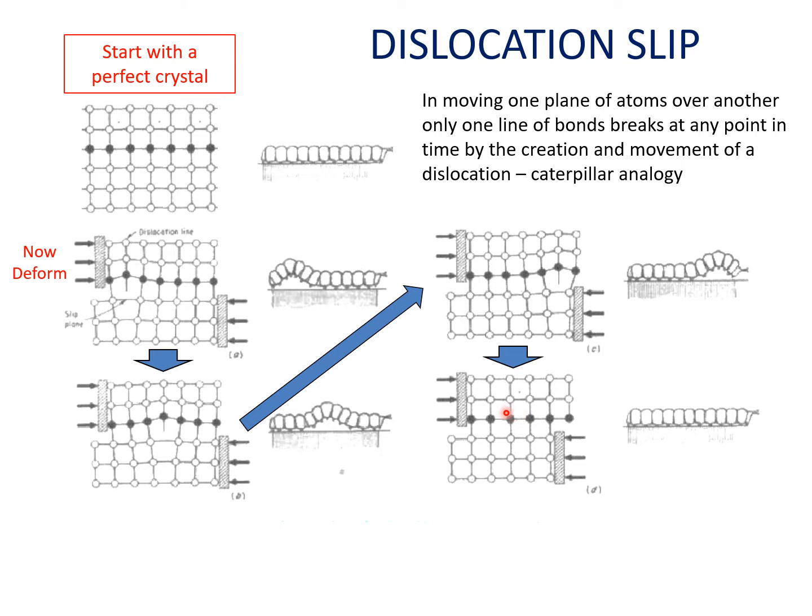Take note, this is something that might come up in your studies, you may come across it a lot. The deformation by dislocations doesn't change the arrangement of the atoms. There's no orientation change here. Ignore the fact that these are black.